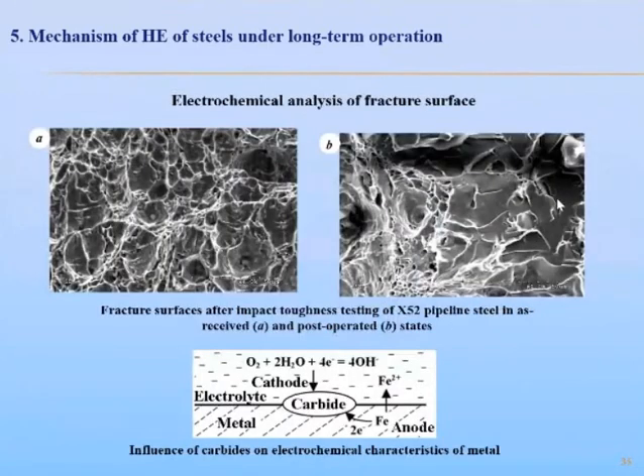And it was assumed that diffusion of carbon not only to grain boundaries but also to various defects inside grains, boundaries of subgrains or other defects took place during long-term operation, and it led to formation of nanoparticles of carbides at these sites also. And under service conditions, diffusion of carbon can be significantly intensified by hydrogen being absorbed by steel. It's well known that hydrogen intensifies diffusion of other elements in steel, including carbon.